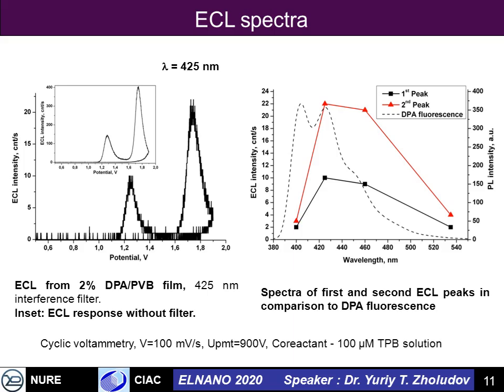In order to check that both waves have emission originating from the same emitting state, spectroscopic studies were done. First of all, using a set of optical glass filters, the emission was measured during the first and second peak of ECL. On the right picture, such spectroscopic data is presented. You can see clearly the first and second peak, red and black. They have the same structure, so the emitting state is the same; only the amplitude is different. If you compare this data with the fluorescence spectra of diphenylanthracene, a clear red shift of the wavelength is visible. But still we are sure that diphenylanthracene is the emitting state, since there are no other emitters in the system.